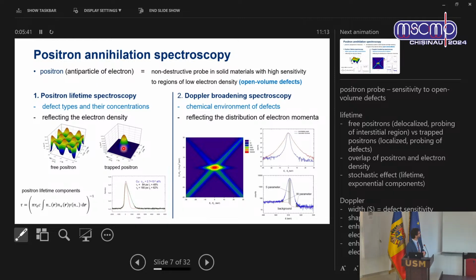The quantity is called the positron lifetimes. You can see it can be relatively easily calculated. And the important thing there is that those lifetime components, the numbers, are unique for each type of defect in the material. It's sort of a fingerprint of a defect. Also, the intensity of this lifetime component carries information about the concentration of the defect.